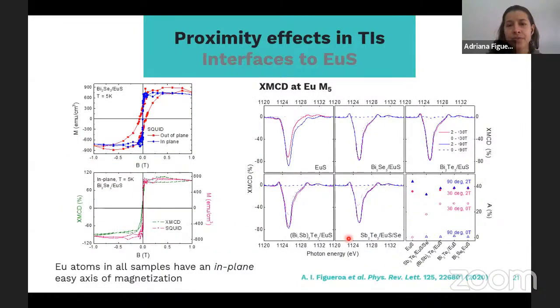Furthermore, we also did some measurements as a function of the angle of incidence to study anisotropy. And then we saw that all samples have an in-plane easy axis of magnetization, not only on XMCD measurements, but also on the SQUID. I mean, both the macroscopic and the microscopic magnetometry match, and they suggest that the europium atoms at the europium sulfide interfaces have an in-plane easy axis of magnetization, not an out-of-plane easy axis of magnetization.